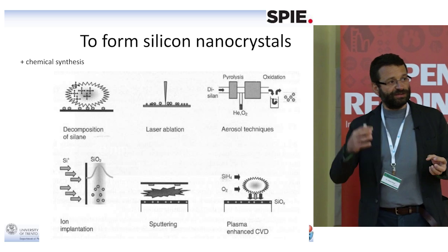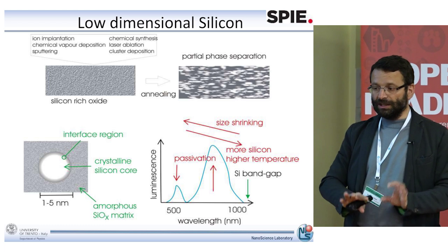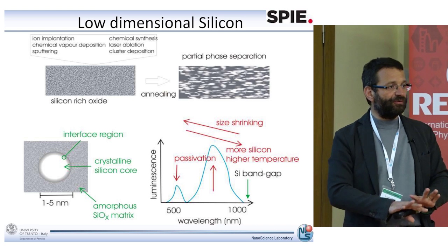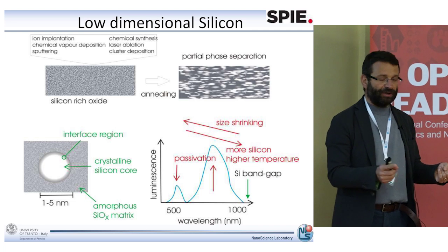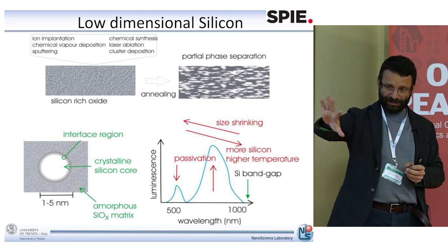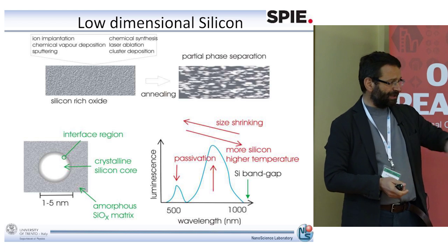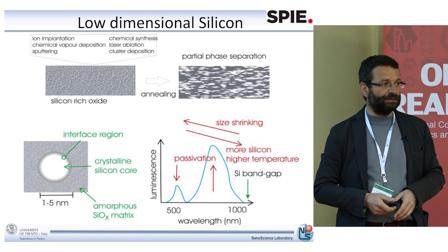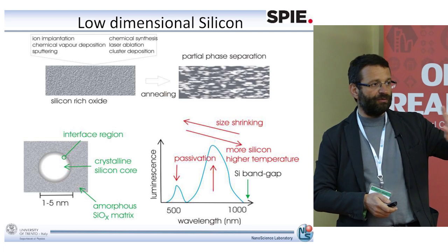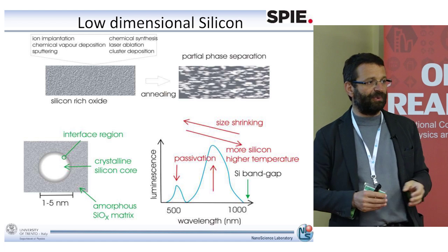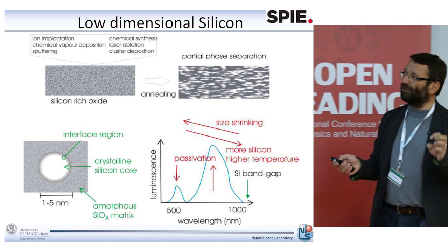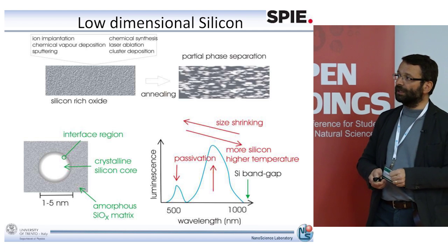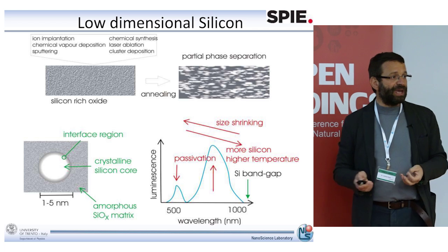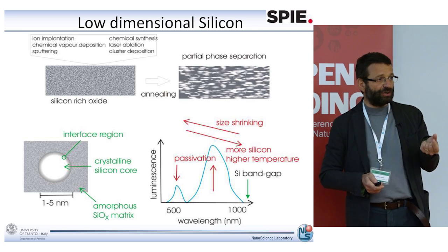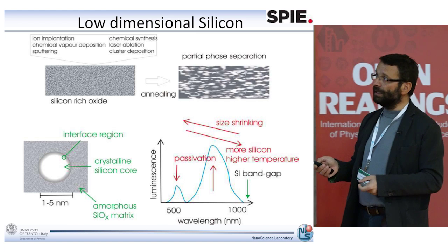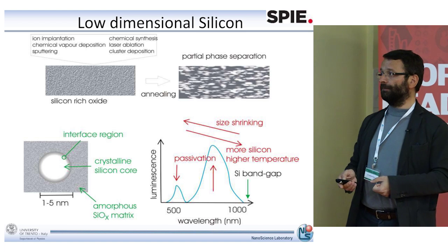And since silicon and silicon oxide are two different materials, they prefer to separate. So you have a phase separation within this silicon-rich oxide, and on one side you have the growing of silicon, and on the other side the growing of silicon oxide. Now you stop the annealing at the very initial phase of this separation. And so what you end up with is very small nanocrystals in the silicon oxide. And you can control the dimension of the silicon nanocrystals by the annealing temperature or by the annealing time.